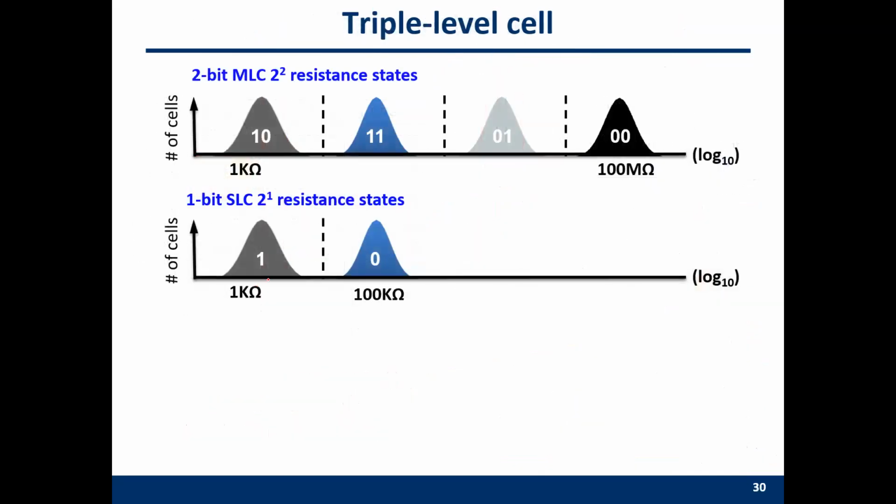So clearly we have a so-called trade-off here. Either we can use multiple level cell, then we double the capacity for free, but we need a larger maximum resistance. We need to use a larger reset energy. The cell endurance is lower.